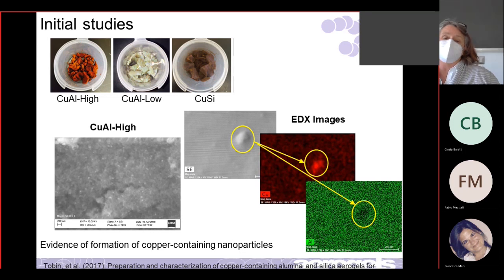And so we did some SEM imaging. And this bar is 200 nanometers. So these are in very close. And we see these specks, looks like little particles in there, probably on the order of 10 or 20 nanometers. So we thought they were copper, but you can't tell just from SEM what it is. It just looks at the surface. But using this energy dispersive X-ray imaging, which is built into the SEM, we can tell what things are.